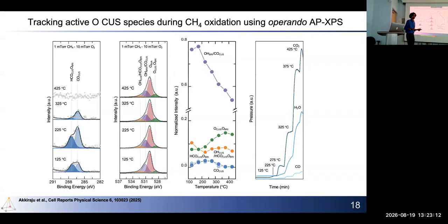So this is only part of the story where we identified the active species as being these oxygen CUS species. We showed that they survived the reaction and still are available at 425 degrees. So what do we do with this information?